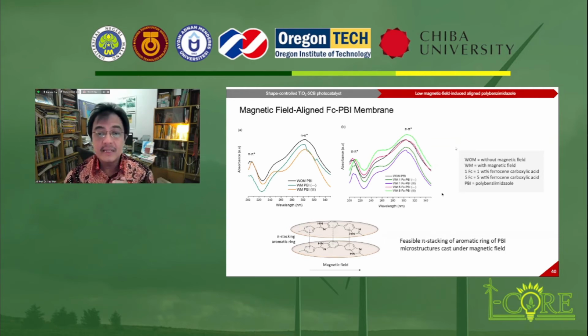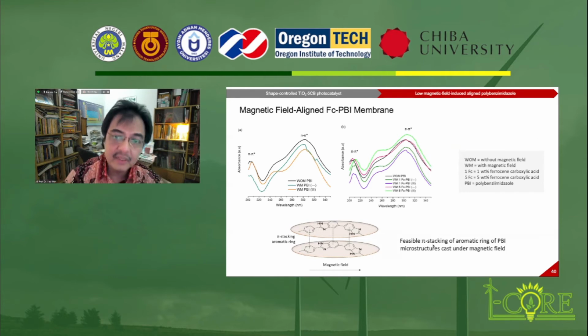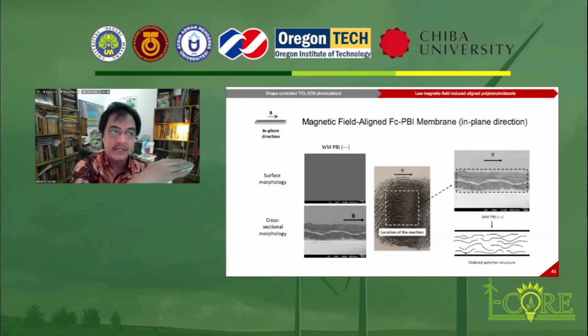It is suggested that the pi stacking results in a decrease in the absorption intensity of the magnetic field treated polybenzimidazole membrane. You can see here the visible pi stacking of the aromatic rings of the polybenzimidazole microstructure cast under the magnetic field. This is the effect of the magnetic field in the in plane direction.